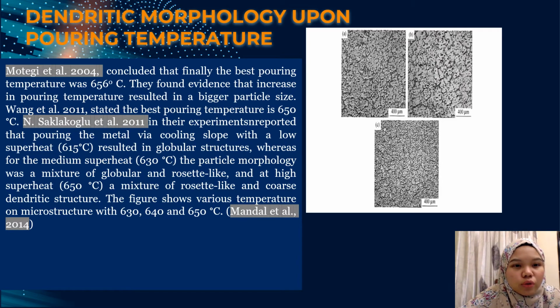And Saklakoglu et al. 2011 reported in their experiment that pouring the metal via cooling slope with a low superheat, 615 degrees Celsius, resulted in globular structures, whereas for the medium superheat, the particle morphology was a mixture of globular and rosette-like, and at high superheat, a mixture of rosette-like and coarse dendritic structure. The figure shows the effect of various temperatures on microstructure with 630 degrees Celsius, 640 degrees Celsius, and 650 degrees Celsius, cited by Mandal et al. 2014.